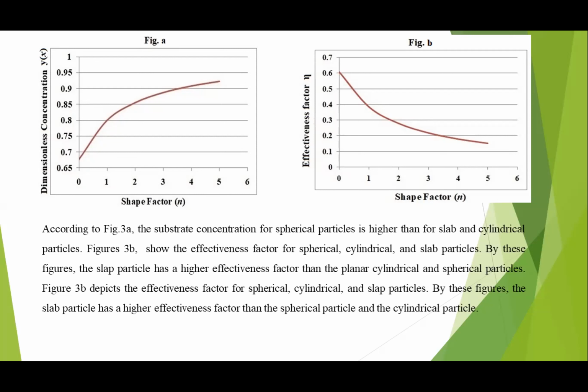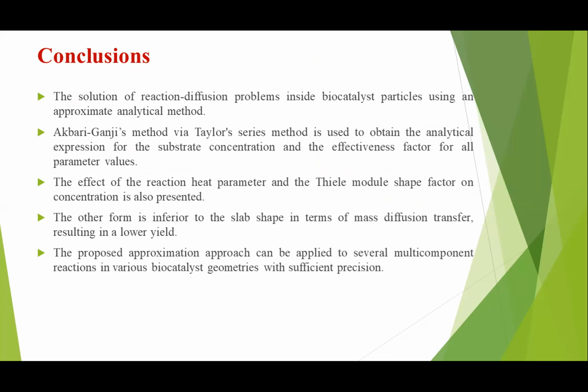So by these observations, we conclude that the solution of reaction diffusion problems inside biocatalyst particles can be obtained using an approximate analytical method called the Akbari-Ganji method. This method is solved via Taylor series, and it is used to obtain the analytical expression for the substrate concentration and the effectiveness factor for all changes in the parameter values. The effect of the reaction heat parameter and the Thiele modulus shape factor on concentration is also presented in this work. The other forms are inferior to the slab shape in terms of mass diffusion transfer, resulting in a lower yield. The proposed approximation technique can be applied to several multi-component reactions in various biocatalysis geometries with sufficient precision in the parameters.